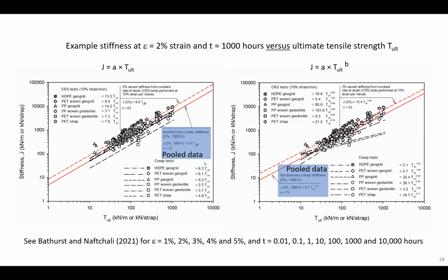If you take all the data together, and we can call this pooled data, then there's a linear relationship again, and that coefficient of proportionality is about 5. So you ask yourself, so what? Well, the thing is, this high quality constant load creep test data is not always available, but we always have the ultimate tensile strength of the material available. So if you know what that is, you can use this pooled value of 5 times T ult as a rough estimate of the stiffness of the material. If you know what the product classification is, you can get a tighter approximation. And if you actually have product specific creep testing, of course, you can use that data directly.